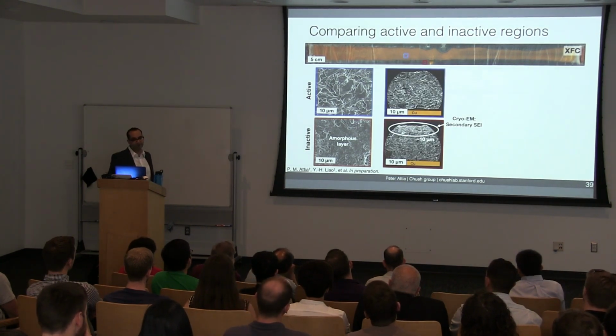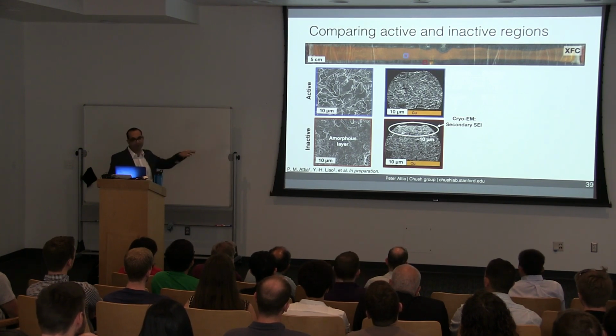We then perform tomography of the electrodes. Tomography is basically the same thing as a CAT scan. If you look at the cross-section, we again see that the active region looks pristine, but the inactive region appears to have this surface layer that extends around 10 microns into the depth of the electrode.